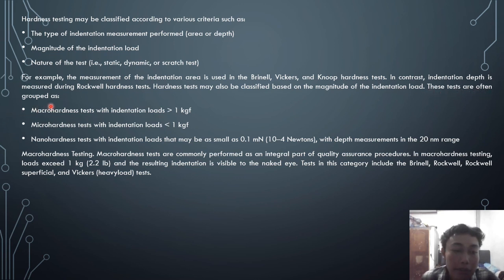These tests are often referred to as macro hardness tests, with indentation loads more than 1 kgf. Micro tests have indentation loads less than 1 kgf. Nano hardness tests have indentation loads that may be as small as 0.1 millinewton or 10⁻⁴ newtons, with depth measurement in the 20 nm range. Macro hardness tests are commonly performed as an integral part of quality assurance procedures. In macrohardness testing, loads exceed 1 kilogram or 2.2 lb, and the resulting indentation is visible to the naked eye.